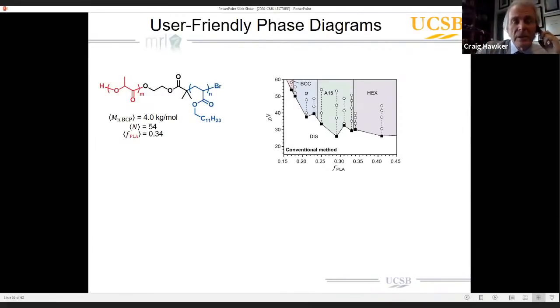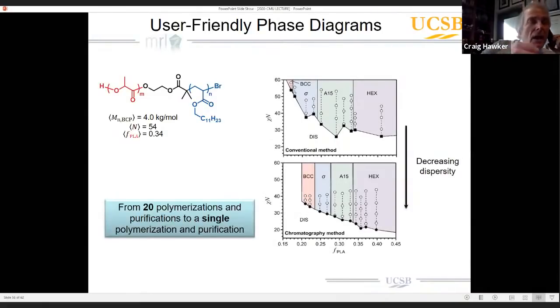And now, using a much simpler and quicker procedure, Cheng and co were able to take a single polymerization, then purify it in about a day or so, and you can see that we get a fairly different phase diagram that, in my opinion, is a much better representation of what the morphology is actually like for these diblock copolymers. You can see the very stable BCC phase, very stable sigma phase, the A15 phase, and then the hex phase. So again, really looking into new morphologies for these simple diblock copolymers.